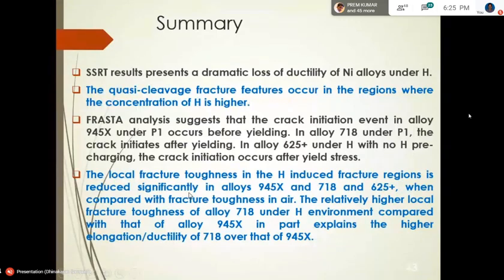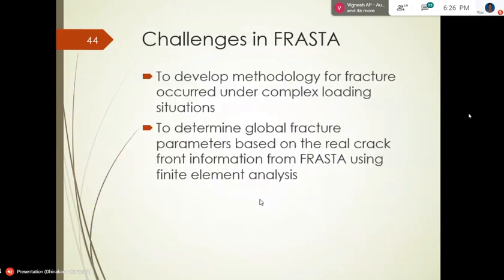So what this tells us is, of course, the SSRT shows loss of ductility, but there are some gaps which we need to address. And FRASTA, fracture surface topography analysis, is helpful to do some postmortem analysis. It's a technique that can be used to do fracture replay analysis using the topography of the fracture surfaces. And also we can see the local fracture toughness between different alloys. So that's a pretty useful thing to do. We can also understand the effect of microstructure locally. We can bring a correlation and understand the microstructural issues.